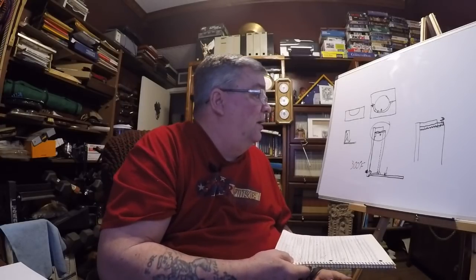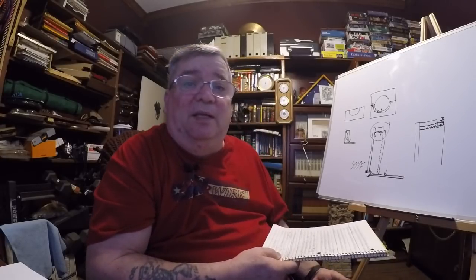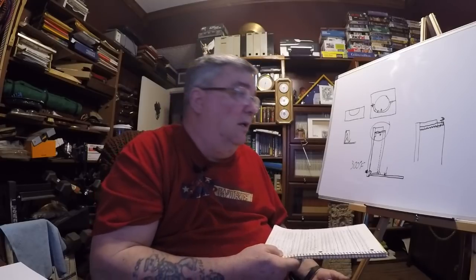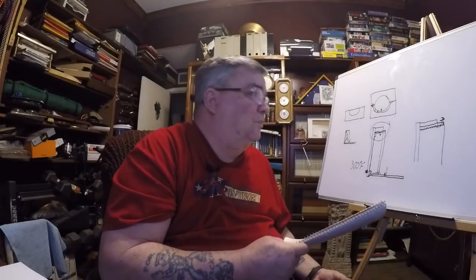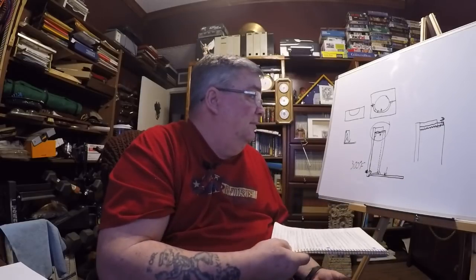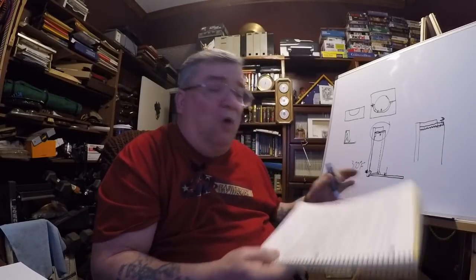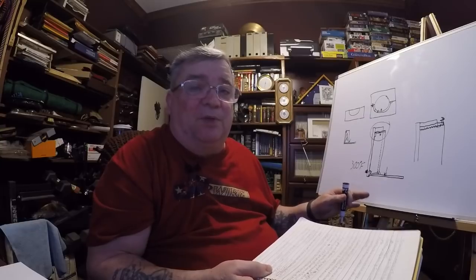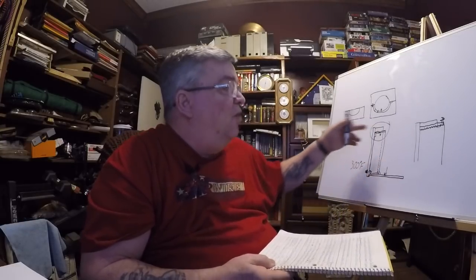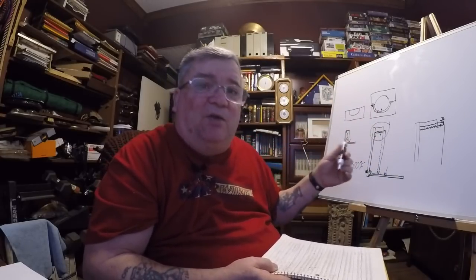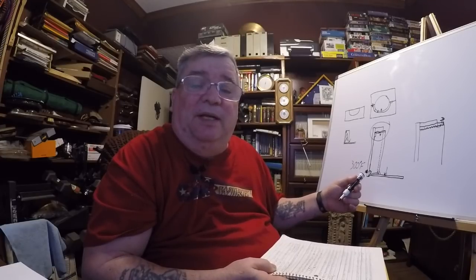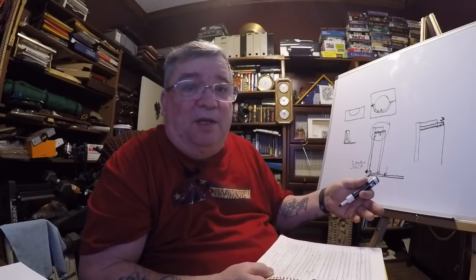I never understood it, but you had to go by the instruction put out by the NDT, non-destructive testing lab, and so that's the reason why. Don't bring it up to tin, or rather the melting temperature of tin. You're going to make this ready to receive the Babbitt, and the Babbitt itself, once you introduce it into the gap in there, into the void, is going to melt the tin and allow the Babbitt to adhere, or rather mix with the tin coating, which is bonded with the steel.